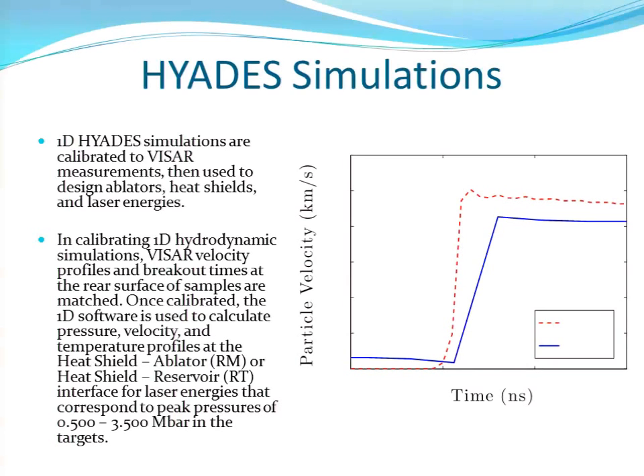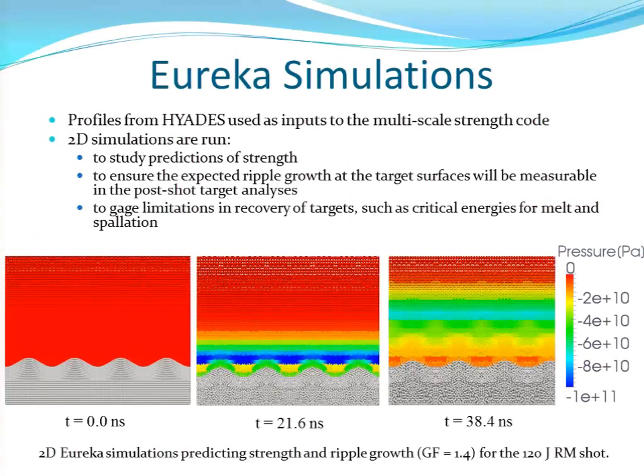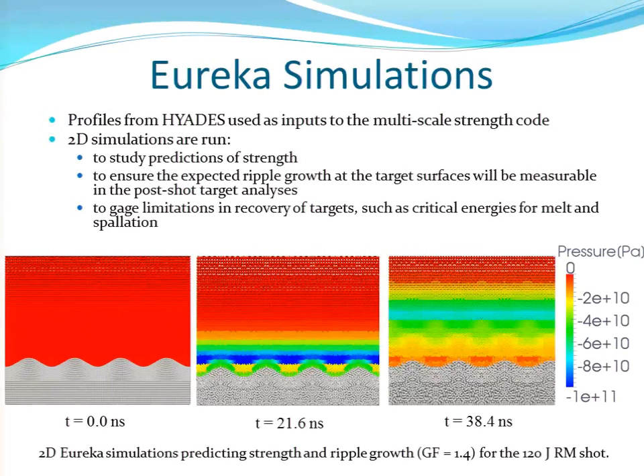We can make sure that after the impact occurs there's actually enough growth that post-shot we could measure the targets and confirm that there's actually growth there. We also want to avoid certain things like melt and spallation. This is some more on the target characterization done post-experiment. One of the problems with these experiments is that we can't get the growth factor as a function of time — we just know what the ripple size was before the experiment started, and then we get the sample afterwards and get a final measure of growth.